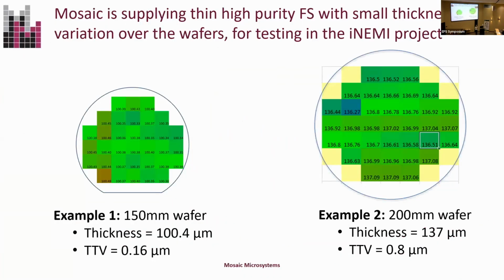So the point here is that Mosaic is actually providing very thin fused silica with very tight TTVs, and these are pretty remarkable numbers. This is a 150 millimeter wafer with a better than 0.2 micron TTV over the whole wafer. So we've mapped it, and we can provide even 200 millimeter wafers. Over that whole wafer, the TTV is much larger. But if you're cutting out those same size squares, in any one square the thickness variation is small enough that they can use it for this reference material. Or at least they're proposing to explore that.